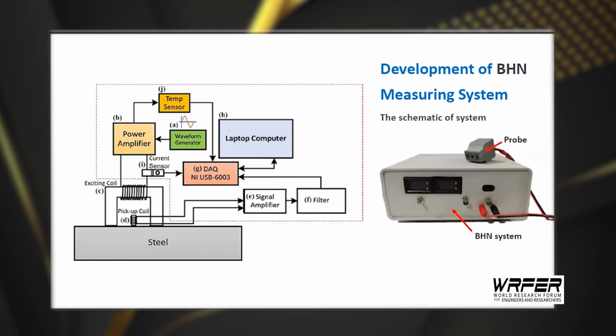Then the BHN signal caused by magnetization was measured using the pickup coil. A signal amplifier and a low pass filter were used to improve the BHN signal obtained from the probe. The current and temperature sensors were used to monitor the exciting current and working temperature of the circuit, and also give feedback to the processing unit. Sensing signals were received via a data acquisition, or DAQ, interface with the personal computer. Data and signal processing were performed by LabVIEW programming.